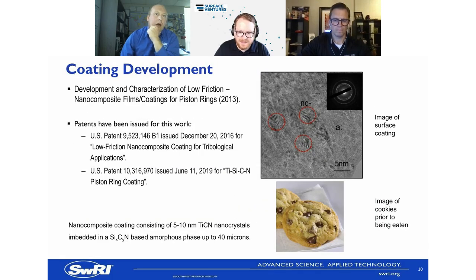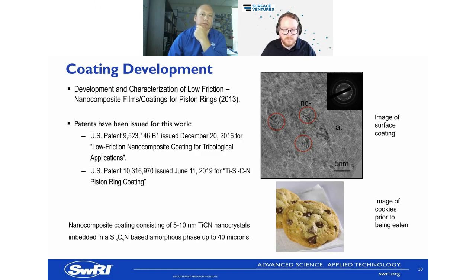That's 5 nanometers that you're looking at there. No, it didn't affect the engine performance at all. These things are embedded in there, but it's so small on the 5 nanometer scale that particles don't create a problem. Was there a roughness measurement made before and after coating? Yes, it was. I didn't put that in. It was slightly smoother afterwards, but not by much. And we had to use white light interferometry to get those measurements because of the small scale.